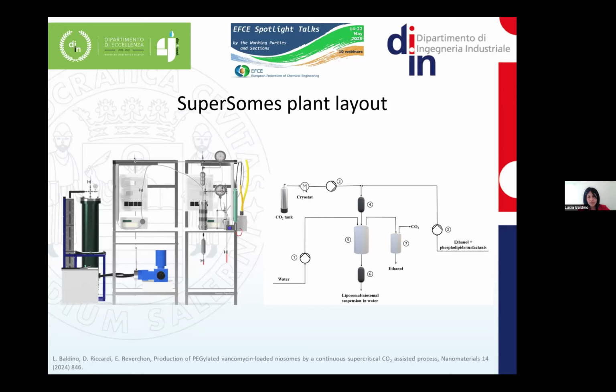So in the high-pressure vessel, we have gas-like mass transfer phenomena, and therefore on the fly, water droplets are surrounded by a first layer of lipids thanks to the interaction of the polar heads of lipids with water, forming the so-called reverse micelles. When these micelles fall at the bottom of the vessel, where an excess of water and lipids is present, we have the formation of the second lipidic layer forming the vesicles, and in a continuous way we can withdraw from the bottom of the vessel the aqueous suspension of vesicles.